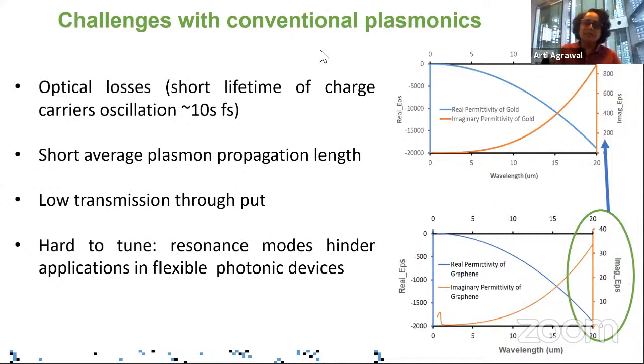So if you look at the right-hand side where I've got two graphs, on the top, you have a plot of the real part of the permittivity versus wavelength. And on the bottom, you have the same plot, but for graphene. So if you compare the right-hand side y-axis of gold and graphene, you see that the imaginary part of the permittivity for gold is an order of magnitude or larger than that of graphene. So in graphene, the imaginary part of the permittivity, which is related to the loss, is about 20, while in gold it is about 400 or 600. And because of that, the loss in gold is much higher.